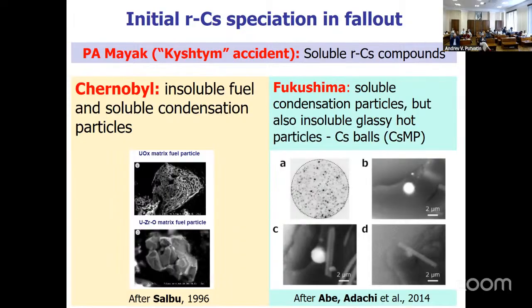First, in the case of the Kyshtym accident, or Mayak, we had soluble, mostly soluble radiocesium compounds. In the case of Chernobyl, we had nuclear fuel particles, which are destroyed on a time scale of about 2-3 years. In the case of Fukushima, a substantial part of radiocesium was deposited in the form of glassy hot particles, or cesium balls, or cesium microparticles. And here you can see pictures of these particles. This is the air filter. These are the particles themselves, and so on.